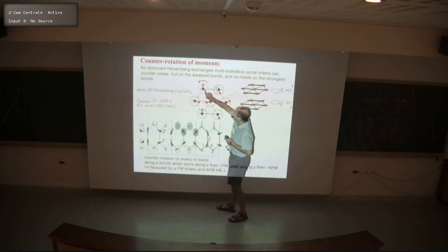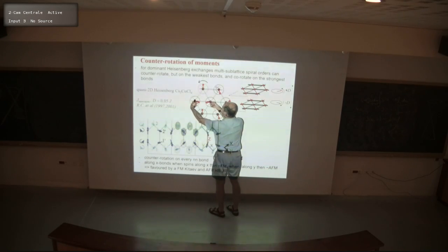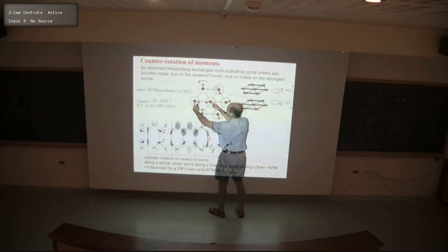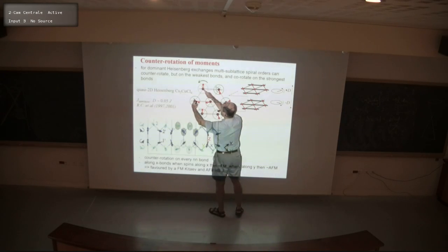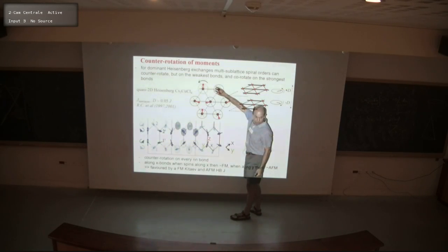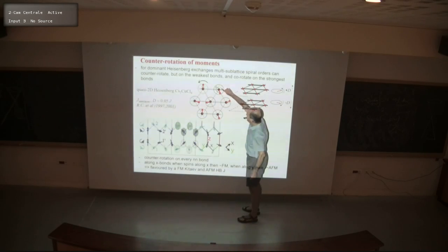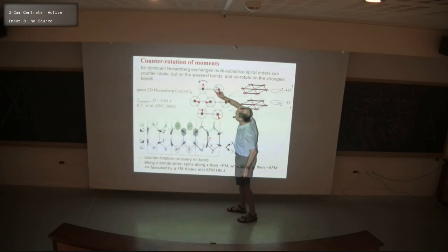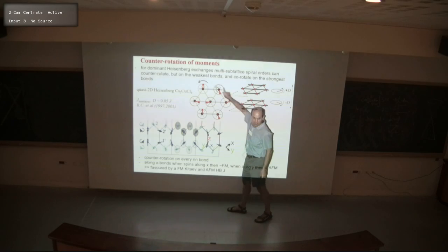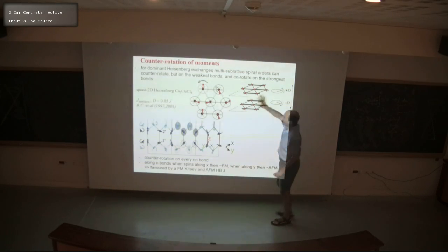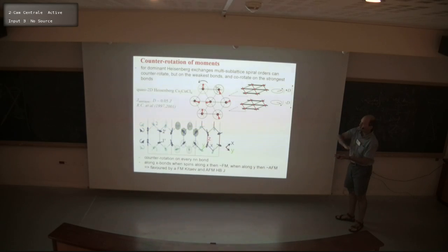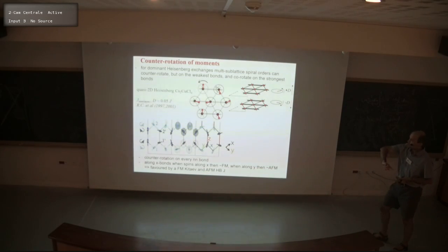So if I just take these 3 spins, and this is the dominant interaction, that's antiferromagnetic. Now, if there's some interaction this way, they lose some energy if they tilt this way, but that's to second order in this coupling, and they gain energy to linear order in this coupling. Now, the question is, what does this do once these are tilted? And so the orientation of this is then chosen to have the same relative angles with these 2 spins as these other ones had. So the whole structure is periodic, and is characterized by a rotation of spins as you move between unit cells.